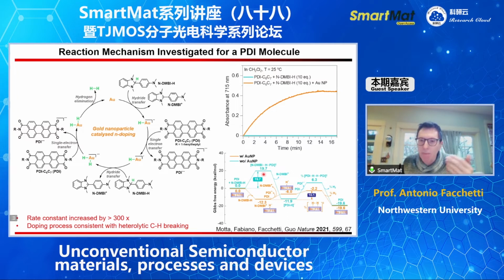And we talk about activation energy. So we monitored the uncatalyzed process. The activation energy is on the order of 20 kcal per mole. Instead, for the catalyzed process, which is shown here in orange, the activation energy is on the order of 10 kcal per mole. And this translates into a huge variation in terms of kinetics, so in speed, between the uncatalyzed process, where basically the reaction doesn't happen if you don't heat it, and the catalyzed process, where the reaction also happens at 25 degrees without any heating.